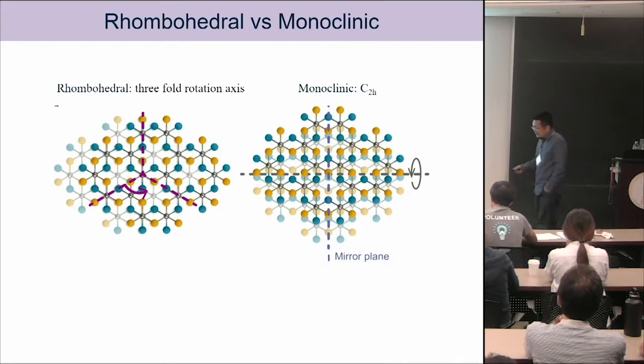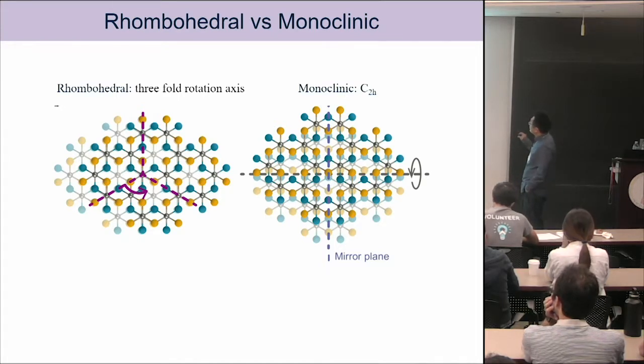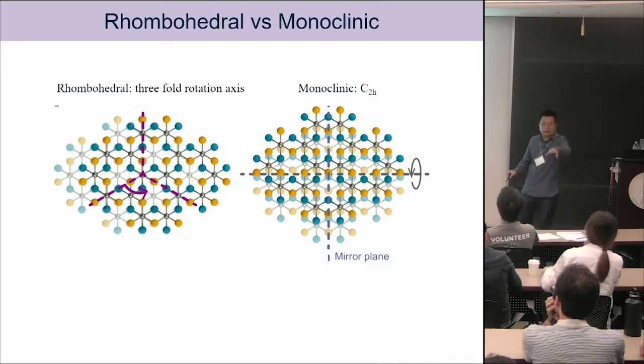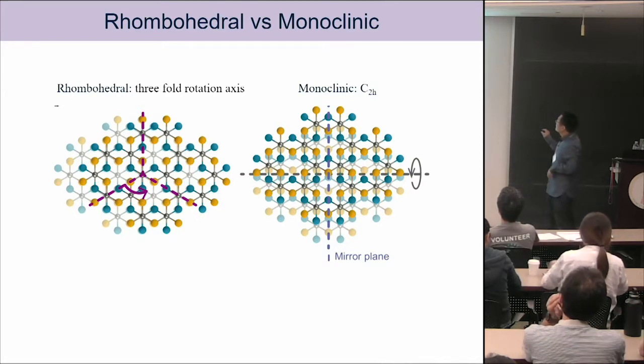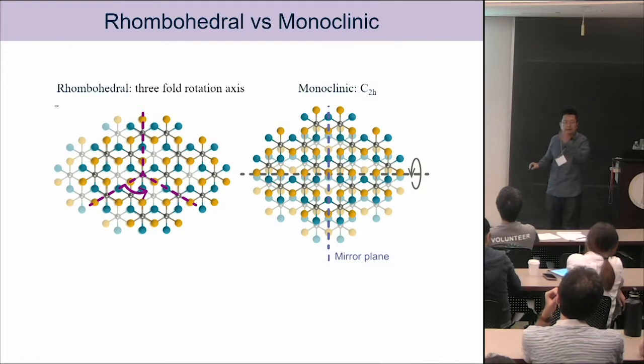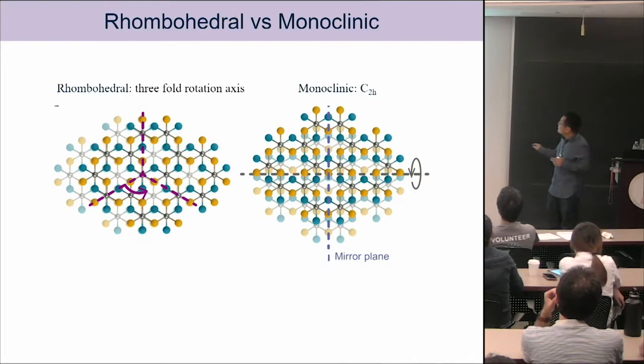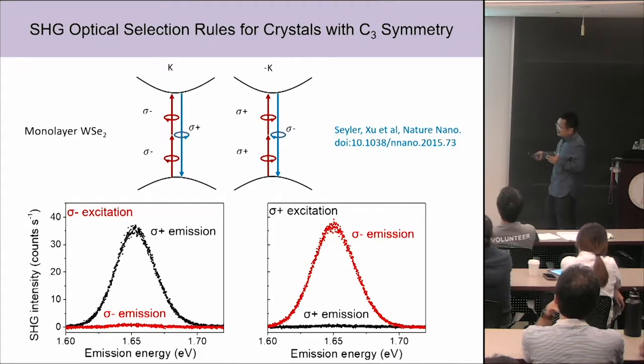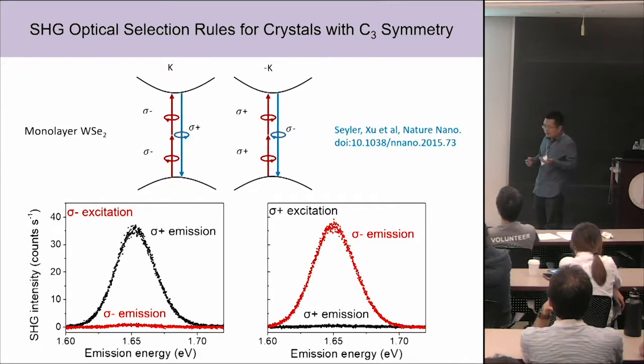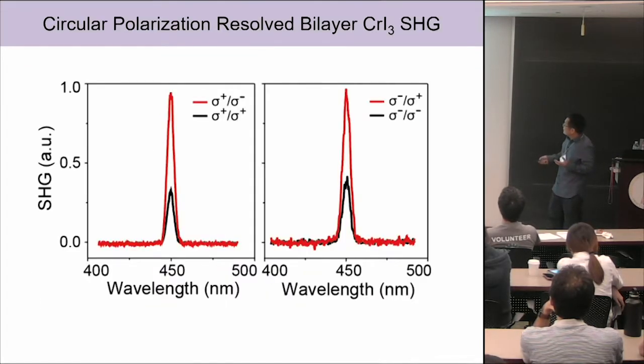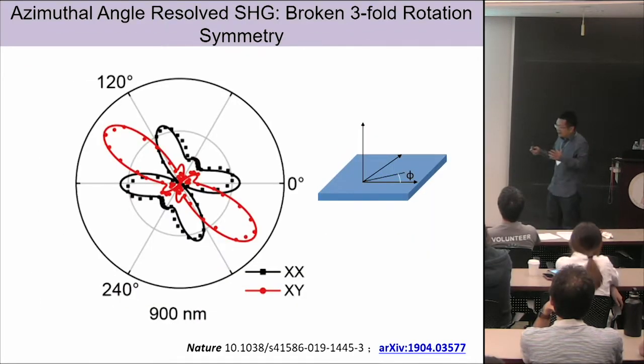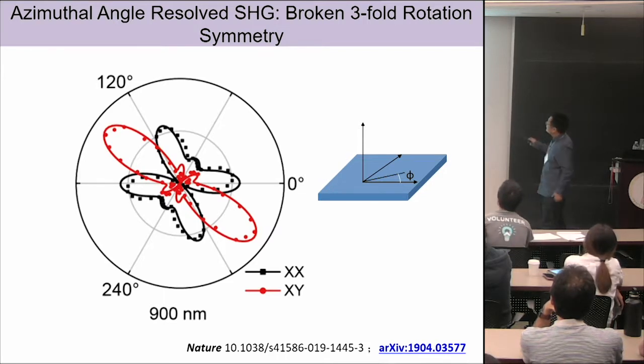Okay, the next is, now we look at the crystal symmetry difference between the rhombohedral and the monoclinic structures, right? Rhombohedral has this 3-fold rotation symmetry, but the monoclinic is C2h. What it means is you only have a 2-fold rotation symmetry and a mirror plane. Then we can use the angle-resolved second harmonic generation to resolve the symmetry of the crystals.